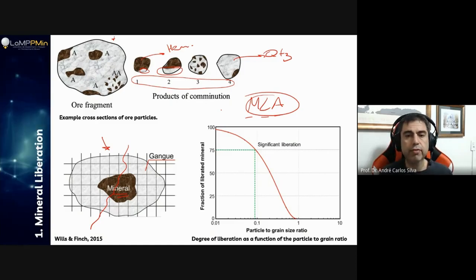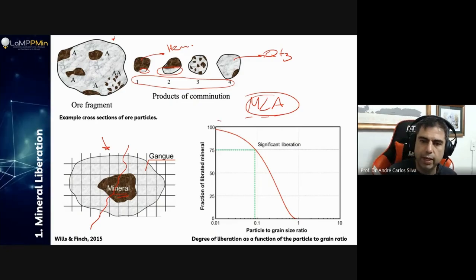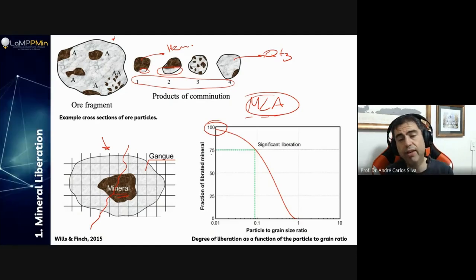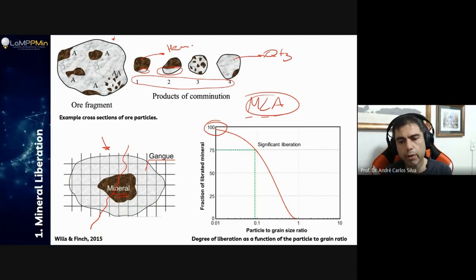And analyzing this mapping, I'm going to come to this graphic. So this graphic correlates for me the size of the particles and how much is going to be the liberation degree of our material. So one thing, it's quite understandable that if I have very, very small particles, then probably I have 100% liberation. And that's true. And that's why I'm over here, almost 100%. And if I have only coarse particles, probably I have 0% of liberation.